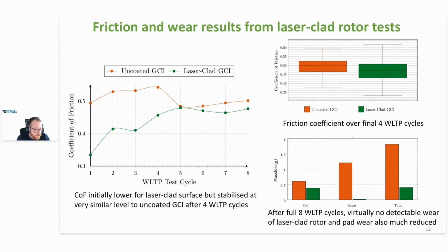And perhaps because of this initially low coefficient of friction, pad wear for the laser-clad sample over the full 8 cycles is reduced, as we can see in the figure on the bottom right. But more importantly, wear of the laser-clad disc is actually reduced to a level that is barely detectable.